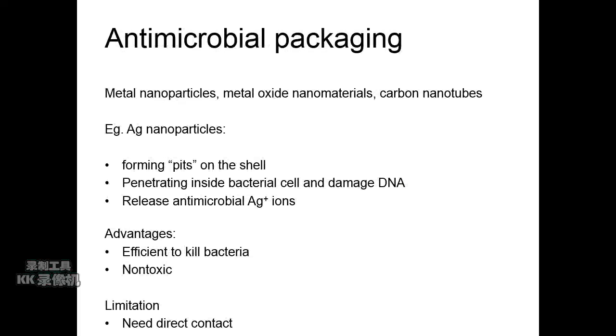Next, for the antimicrobial packaging materials. The most commonly used are the metal nanoparticles, metal oxide nanoparticles, and carbon nanotubes. Among them, silver nanoparticles are used a lot for these applications because they are non-toxic. The silver nanoparticles can interact with the surface of the bacterial cells and form pits on the surface, then penetrate the bacterial cells and damage the DNA.